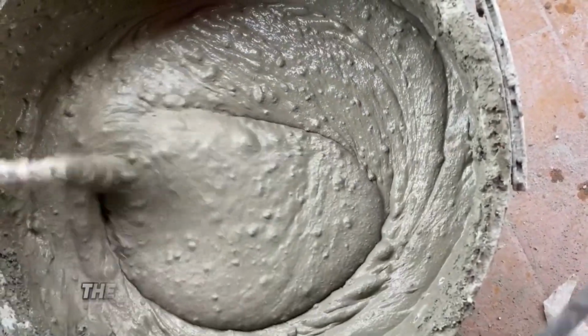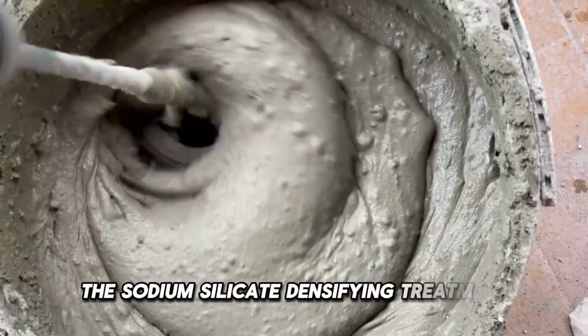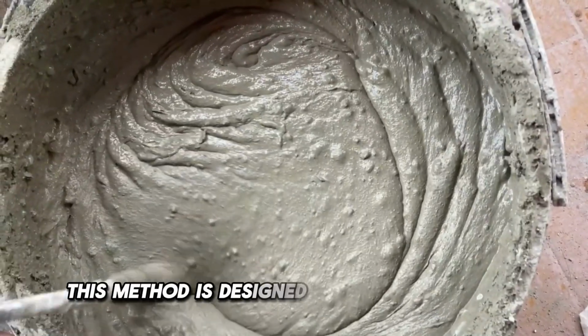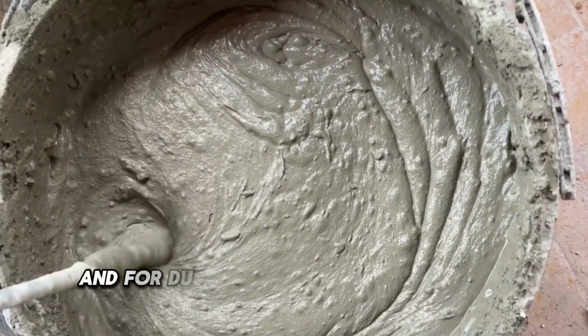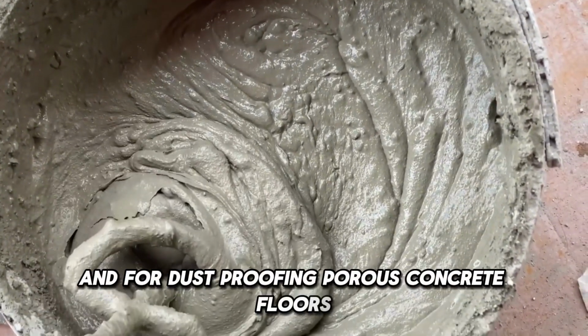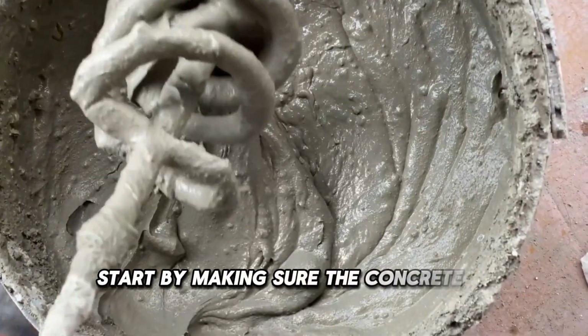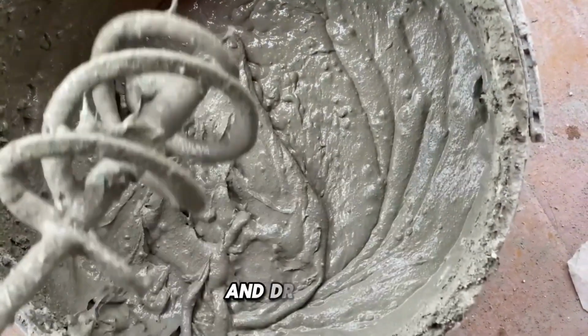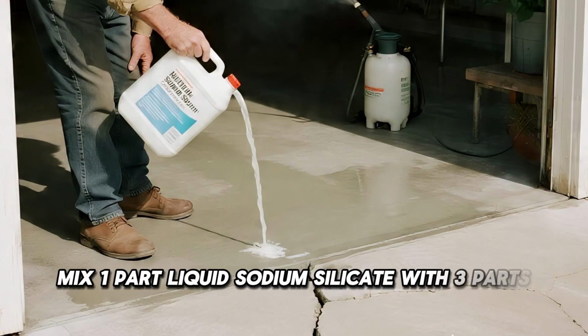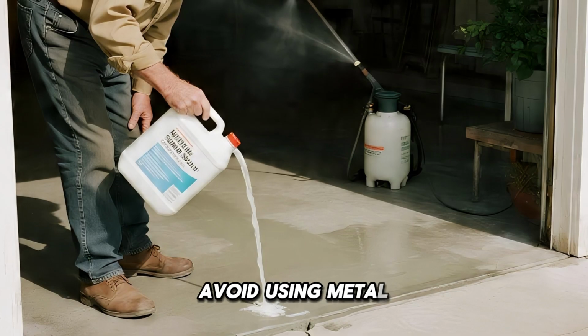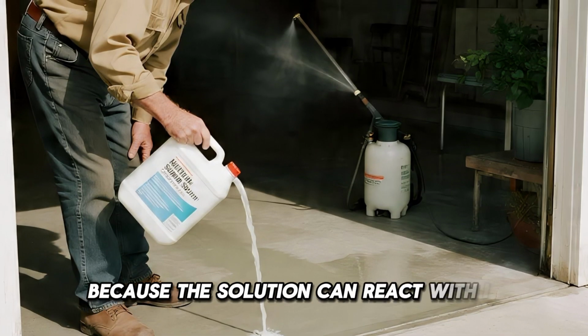Method A. The sodium silicate densifying treatment. This method is designed for hairline cracks and for dust-proofing porous concrete floors. Start by making sure the concrete is completely clean and dry. Next, mix 1 part liquid sodium silicate with 3 parts water inside a plastic container. Avoid using metal because the solution can react with it.